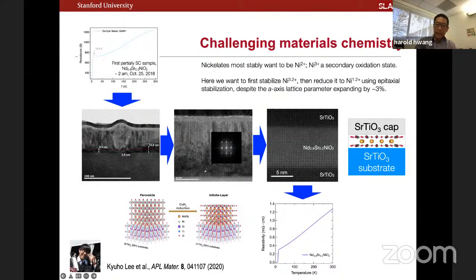And so the last key step for us was then to make a perovskite heterostructure and further cap it with, in this case, the substrate is strontium titanate and more strontium titanate on top. I should mention in our reduction conditions, that component doesn't do anything. And so we get this proximity effect from both sides, and we can stabilize, depending on the details, somewhere between 10 to 15 nanometer thick single crystal infinite layer nickelate. So if you're interested in these details, we discussed this in this paper, but schematically what you see here is that idea that we're deintercalating these planes of oxygen, stabilizing these thin films, and indeed this system becomes superconducting.